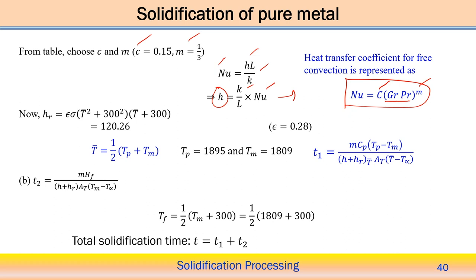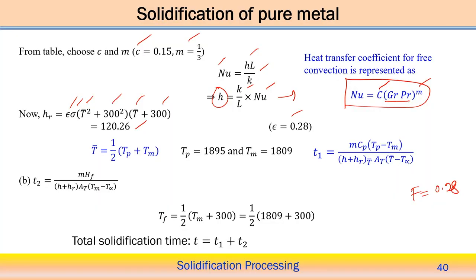Once we get the H value, the heat transfer coefficient, then the radiative heat transfer coefficient can be calculated also like that: the emissivity given is 0.28, and sigma, and T bar square, the average temperature, and T infinity, the surrounding fluid medium air temperature, plus 300. So effective values of the emissivity, instead of taking the F value here, basically F we are considering equivalent to 0.28, the emissivity in this case. We remember that the F value depends on the geometric shape and the emissivity of the surface condition. The surface condition is characterized by the values of the emissivity of the surface. So when you are talking about radiative heat transfer, here with the effective values, F equal to this, and from there we can find this value.